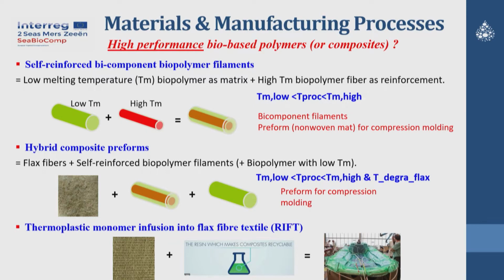For the third type, we didn't develop new materials, but we developed a new manufacturing process. For a big component, such as a wind turbine blade or boat hull, the common material is glass fiber reinforced thermoset composite, usually made by vacuum infusion and VARTM. Instead of glass fabric, we use flax fiber reinforcement in fabric form, and instead of a thermoset resin such as unsaturated polyester, maybe you can use thermoplastic resin, but to decrease the viscosity further, we can use a monomer, which can be polymerized in situ. This is the third manufacturing process.